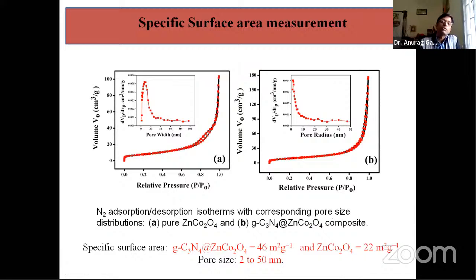And the second thing is you have to measure the surface area as well as the pore size. Surface area has to be checked because, naturally, the larger the surface area of your electrode material, the larger its capacitance will be. That depends upon A, the area of your electrode. It must be large. And that can be checked with the BET measurement technique. In BET, your material is porous, some gas is adsorbed, and from the amount of gas adsorbed, the pore size and surface area are calculated.